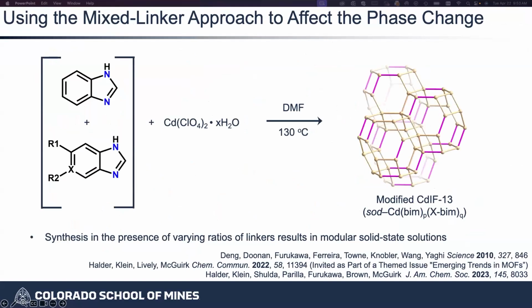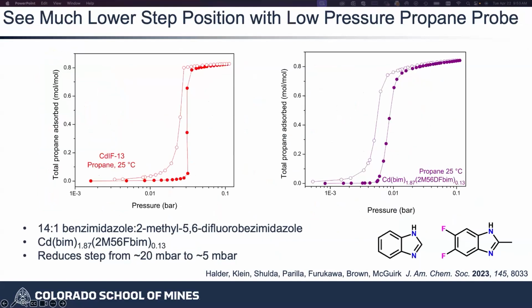And so what we decided to do was take a second organic linker and more or less synthetically dope it into the lattice. What we're really focused on are groups that would invert the electrostatic potential on those organic linkers and weaken the Velcro. Skipping a ton of work that was done, specifically by Origid in my group, what he was able to find is that by doping in this fluorinated linker, where you're inverting the electrostatic potential of those arene rings from CH to CF, you weaken and lower the energy barrier for the phase change. And this became apparent when we were using propane as a low pressure, high throughput probe with the original system.